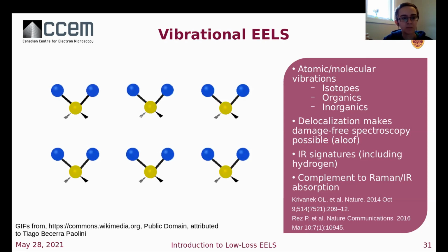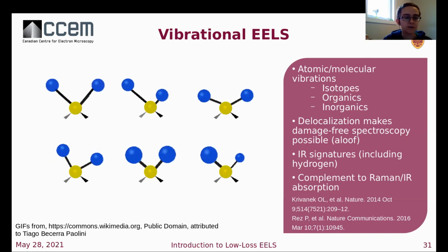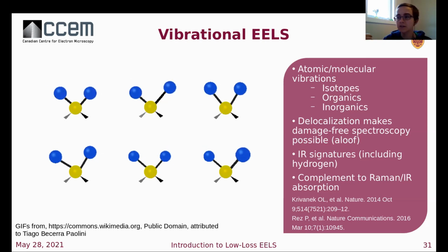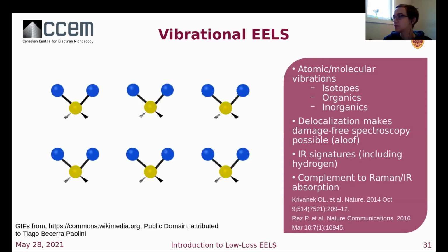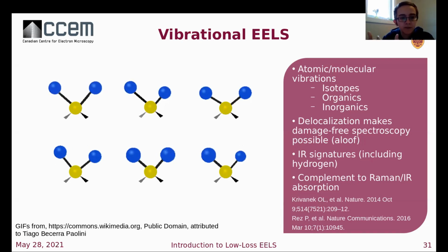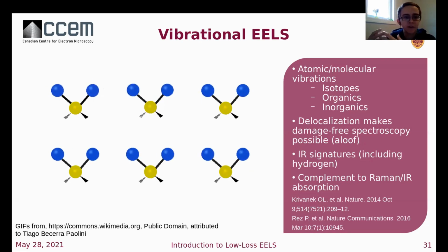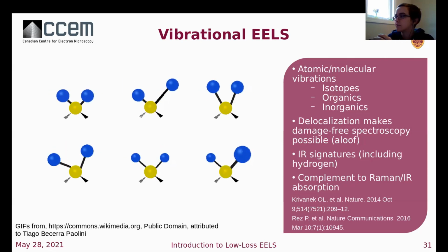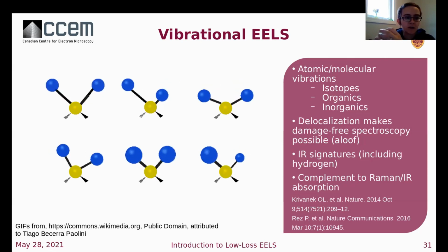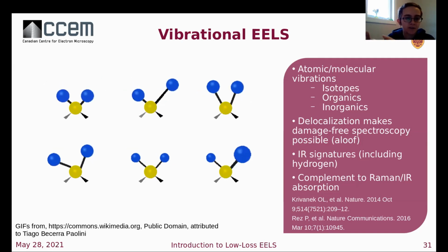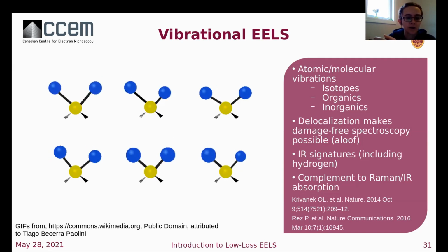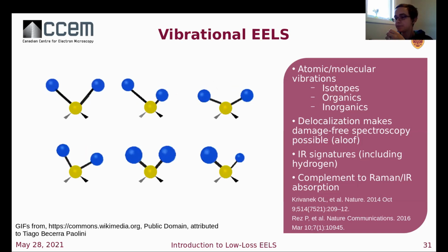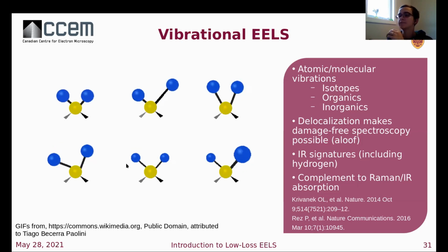This is kind of like a complementary technique to Raman and infrared absorption spectroscopy, in that we're probing the molecular vibrational modes. We may have nanoscale resolution. We do need to worry a lot about beam damage. We gain some advantage from delocalization of the signal from these modes, which means that it's possible to leave the electron beam outside the sample and still acquire information from the sample.